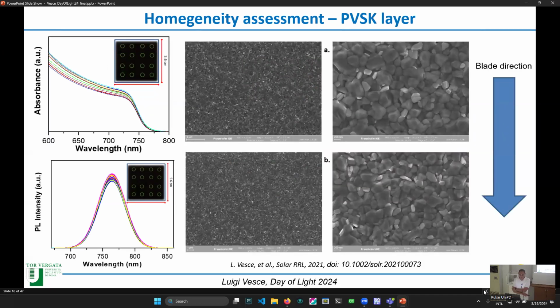Then another homogeneity assessment is to divide the substrate in different spots, in different parts. Here we measure, for example, the absorbance and the photoluminescence at different points to see if we have a big difference. We also check the morphology according to the blade direction, because sometimes if the process is not optimized, you can have some difference at the beginning and the end of the deposition. But here you can see that the perovskite grains are quite homogeneous if we take a picture from the beginning or the end of the deposition.